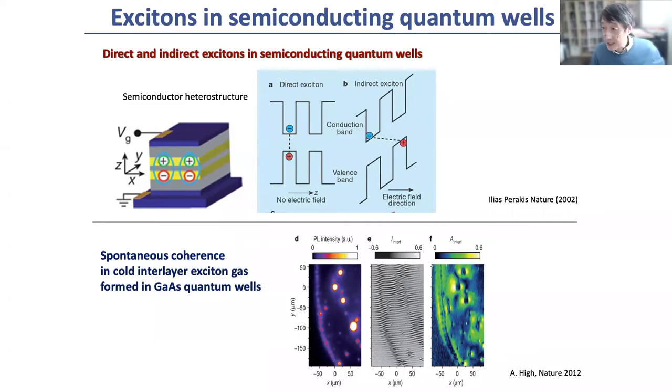However, despite a lot of heroic efforts, it's still a little bit difficult to deal with because in general, in these semiconductor heterostructures, there is strong Coulomb screening due to the relatively high dielectric constant, so the exciton energy is relatively small, something like a millielectron volt. And exciton lifetime is something like 100 nanoseconds. It's probably 1,000 times longer than a direct exciton, but nevertheless, there are some fights we have to go through to really stabilize this in the phase diagram.